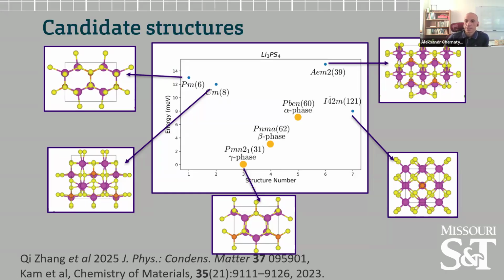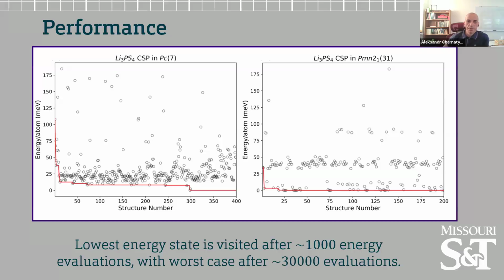Otherwise, gamma phase is the lowest energy phase, and that's precisely what we found. We can look at the performance a little bit. What's shown here is the evolution of the lowest energy structures shown in red, and other dots are other considered structures. This is not a terribly informative graph. I wanted to show one good case, and the good case is shown on the right here, where you can see